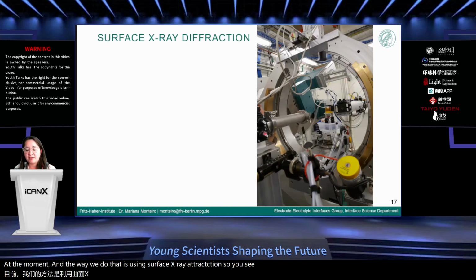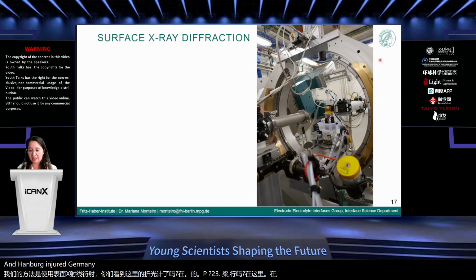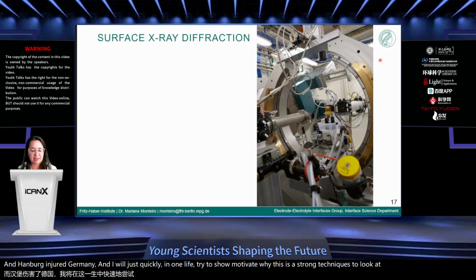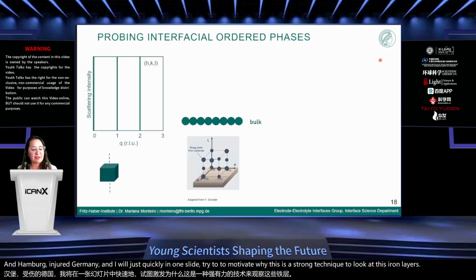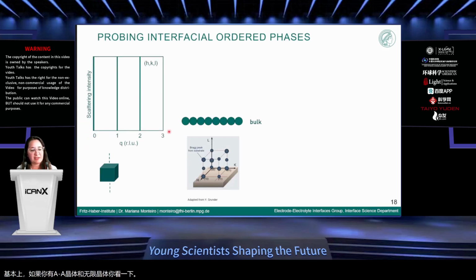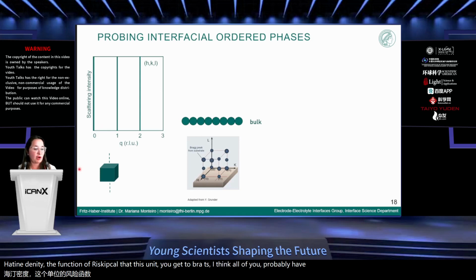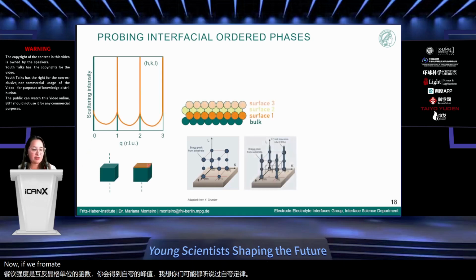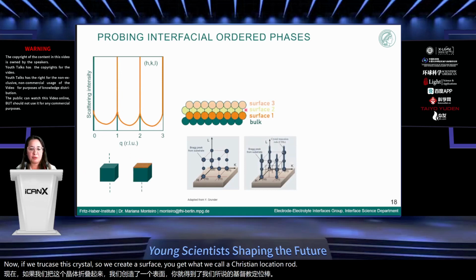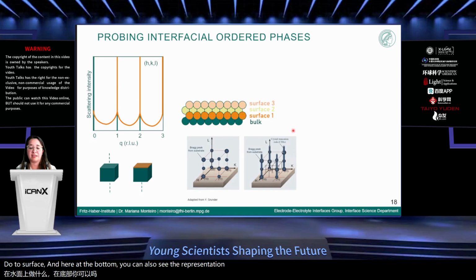So you see here the diffractometer at the P23 beamline in Hamburg, Germany. And I will just quickly, in one slide, try to motivate why this is a strong technique to look at these ion layers. Basically, if you have an infinite crystal and you look at the scattering intensity as a function of reciprocal lattice units, you get Bragg peaks. I think all of you probably have heard of Bragg's law. Now, if we truncate this crystal, so we create a surface, you get what we call crystal truncation rods due to this surface. And here at the bottom, you can also see a representation of that in 3D.